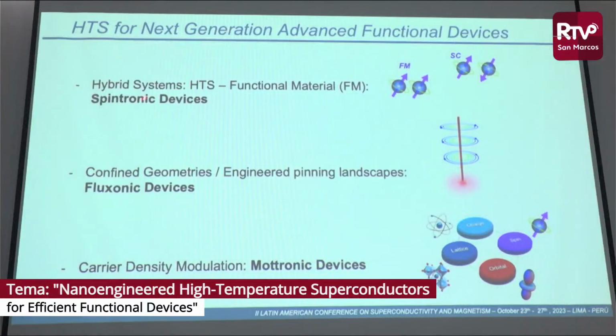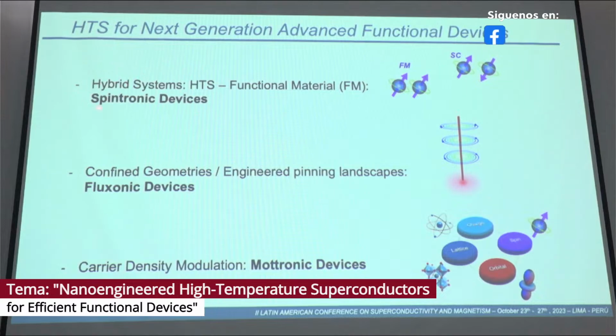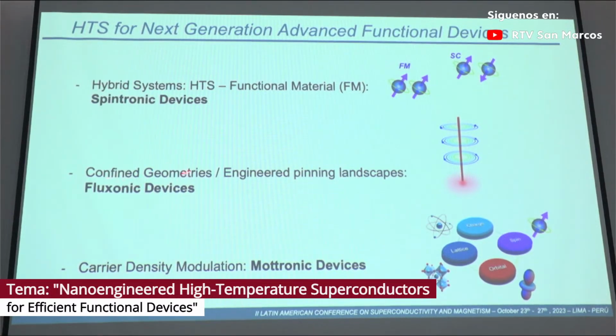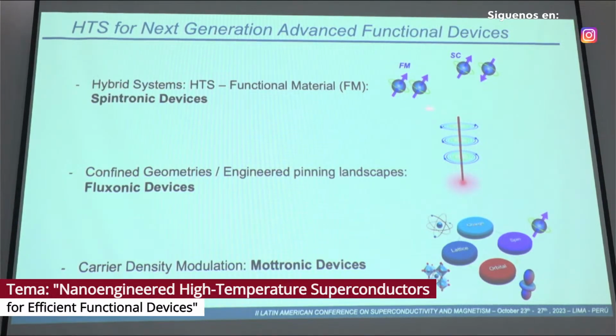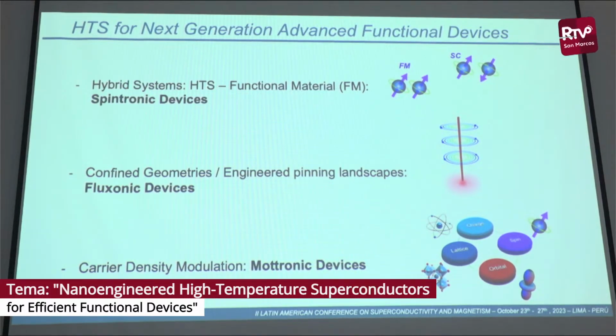One first approach is to use high Tc materials in contact with or combined with ferromagnetic materials in order to try to see if we can fabricate or think about spintronic devices. We also can work with the geometry of the material in order to play with the vortices. The vortices are the quantum flux lines that appear inside the material when we apply a magnetic field, and the motion of these quantum flux lines can also be used in order to fabricate devices.